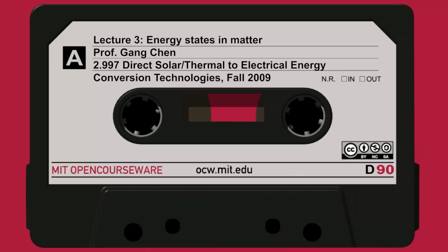If you have a wavelength shorter than that, it doesn't mean much. So that's why my wavelength is limited. This is 2a, while one atomic distance is a. So this is the minimum wavelength you can have. Those are the region of my wave vector, going from negative pi over a to plus pi over a.